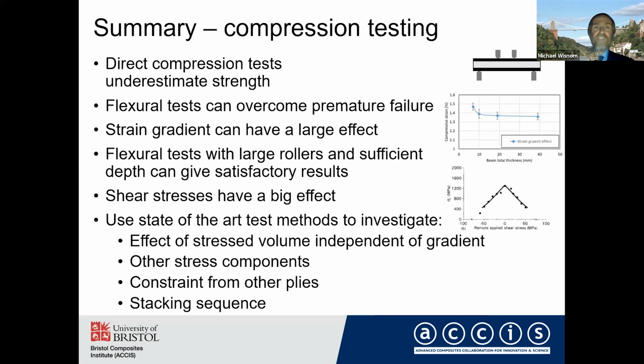So a summary on the compression testing. The direct compression tests underestimate the strength. Flexural tests can overcome premature failure, but the strain gradient can have a very large effect, so we have to be a bit careful there. But flexural tests with large rollers and sufficient depth to overcome that strain gradient effect can give satisfactory results.